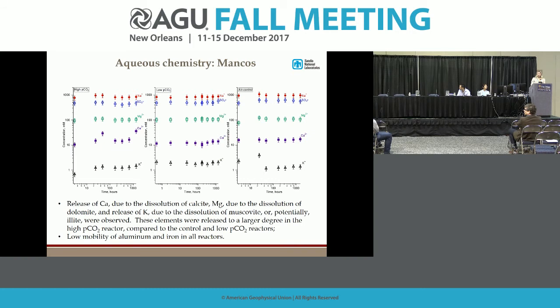And we saw that there was a release of calcium, magnesium, and potassium. So we documented dissolution of calcite, dolomite, and muscovite, and they were more pronounced in the high-pressure CO2 reactor. And interestingly, we saw very low mobility of aluminum. Even though we were dissolving muscovite, we didn't see any aluminum in the aqueous phase, so it probably precipitated right back as an amorphous phase. That may be important for geologic carbon storage if those aluminum phases can precipitate right away and clog pore